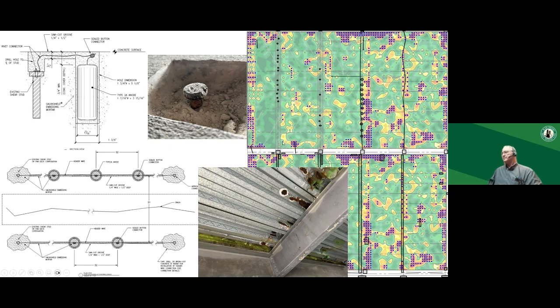So here's how you do it along a crack. You put a string of anodes on one side, a string of anodes on the other side. You attach them to the reinforcing steel on either side and on either end of the string. You don't run it across the crack, because what happens is the wire gets corroded at the crack once the sealant fails. Okay.